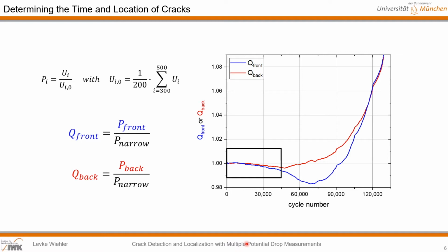At the beginning of the experiment, both quotients have the value 1. A crack is expected as soon as an imbalance between the quotient Q front and the quotient Q back occurs, or a significant decrease or increase in both quotients becomes apparent. Using the potential quotients, a tendency of the initial crack to the front or back side of the specimen is quickly apparent without neglecting the potential difference of the narrow side. There are 3 possible cases for crack initiation, with each case also applying to the opposite quotient.